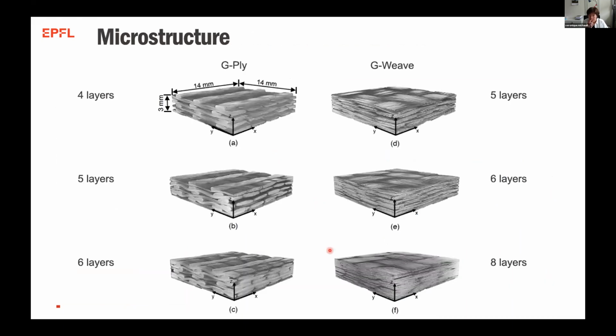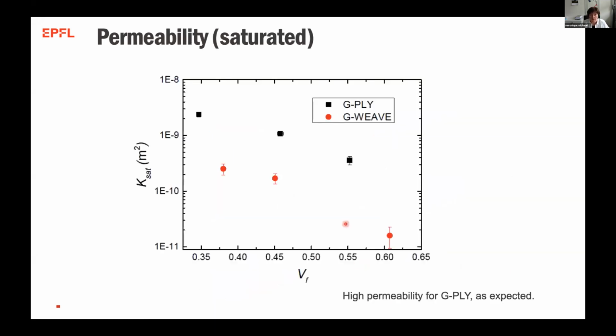We can actually take a look at it here with the CT, and you see that the G-weave, when you compact it, becomes a very compact porous medium with a few pores. And in the G-ply, because of these big tows, when you compact it, you still have really big interstices. And if you do a permeability measurement, you see that the G-ply, as expected, has a high permeability, whereas the G-weave, the normal one, has a normal permeability. This was done for polyamide, which has a reasonably high viscosity, so you can increase the permeability almost by an order of magnitude, and you can go in much easier.